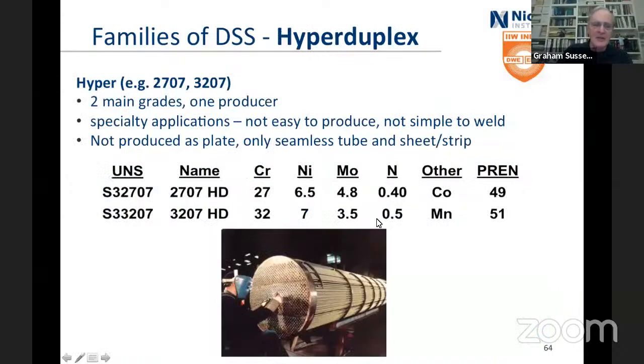And then the hyperduplexes. There's only one producer, 2 grades, and it comes as seamless tube or sheet strip. And that's for reasons of, well, I haven't been told this, but it'll be for reasons of actually heat treatment and so on. And PREs of 49 and 51, so it's really there. A bit of cobalt added there, interestingly, instead of nickel.